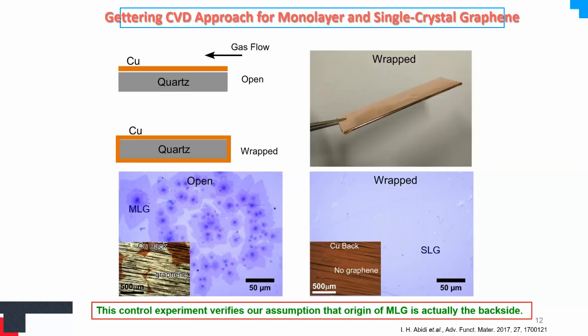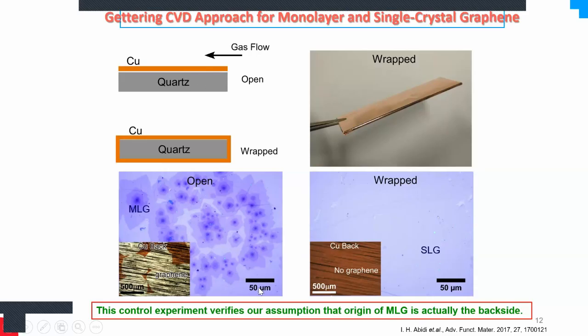So what happened? It was a very stark contrast. You can see in the open configuration we grow, the bottom layer is of course a monolayer graphene, and then you have a lot of these multi-layer patches. But once we do this closed, wrapped configuration, we see a completely single layer graphene. So this control experiment gives us one clue that actually there's something happening at the backside of the copper, which also takes part in the top side growth.